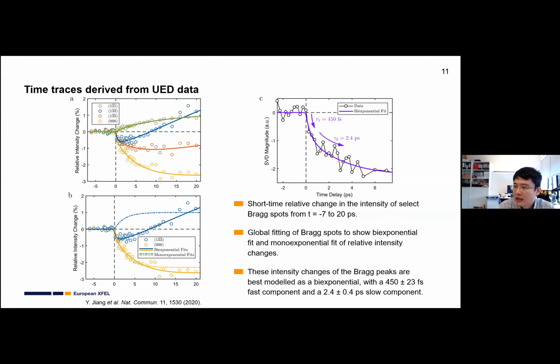So it's also important to show the short time relative change in the intensity of selected Bragg peaks. We use the global fitting of the Bragg spots to show the bi-exponential fit and the mono-exponential fit of the relative intensity changes. And we can see the bi-exponential fit, with a 450 femtosecond fast component and a 2.4 picosecond slow component, can fit our time trace very well. So we have two parts: one is 450 femtoseconds and the second is 2.4 picoseconds.